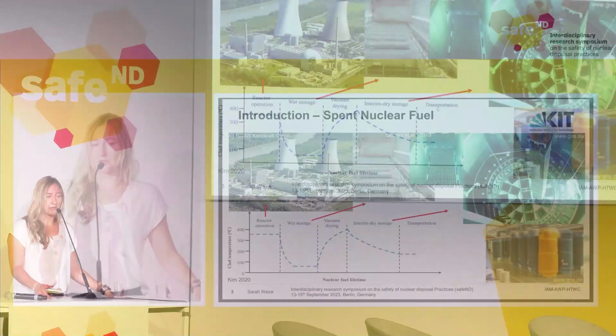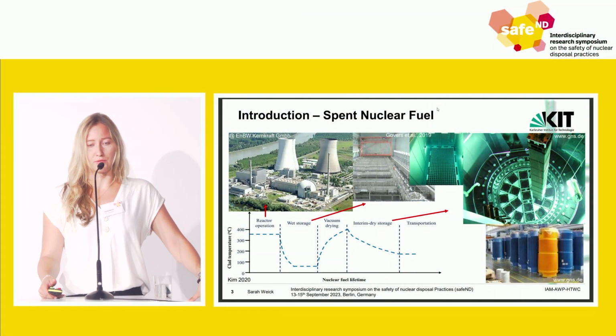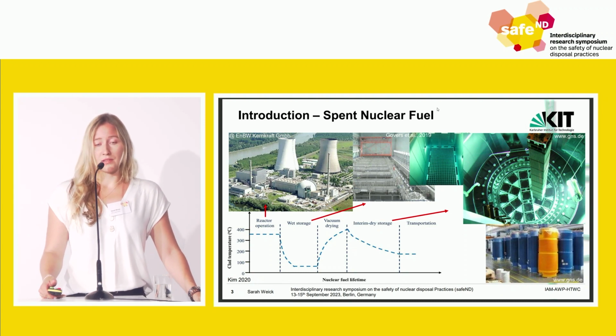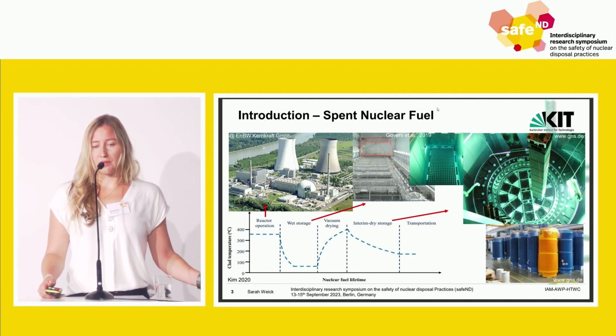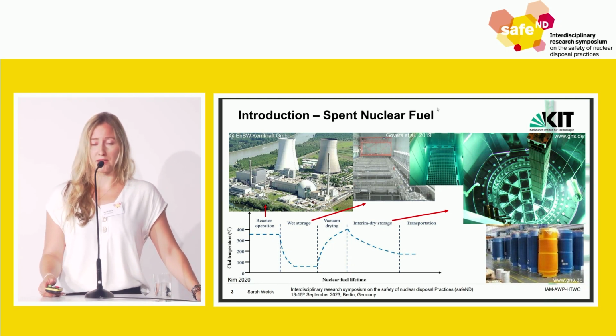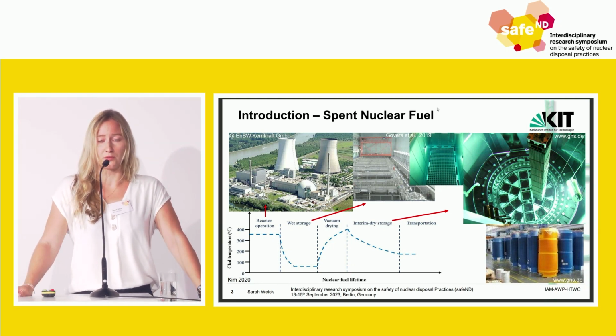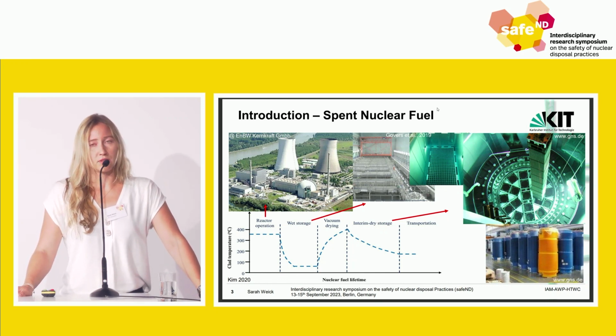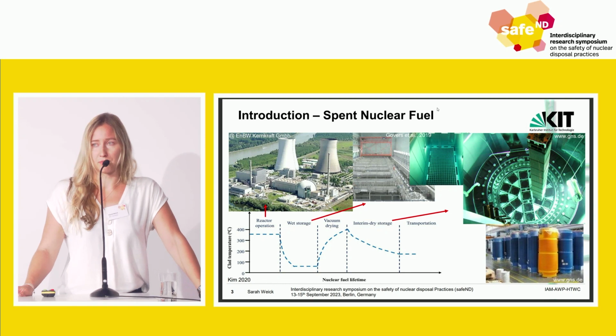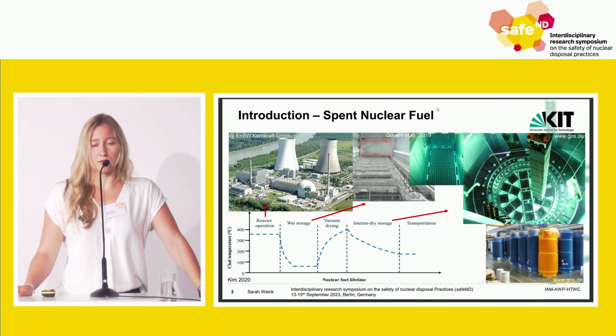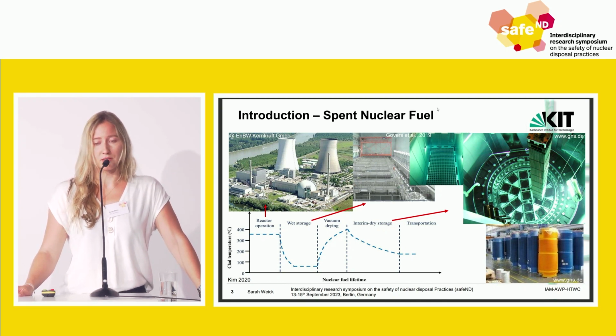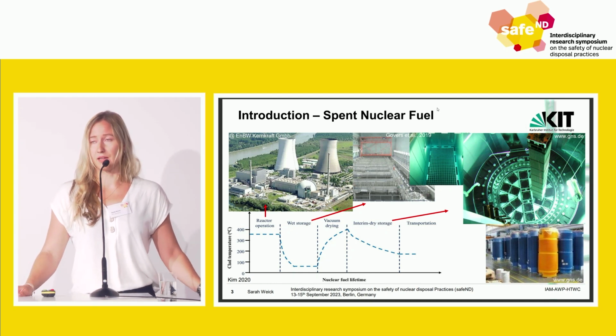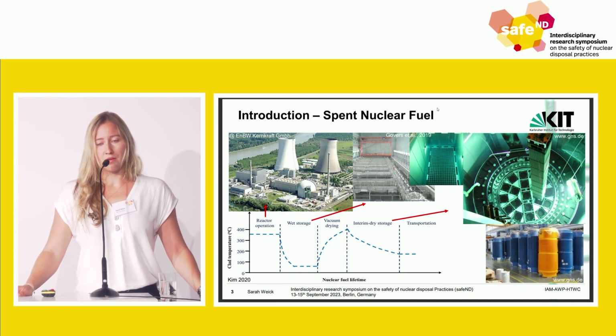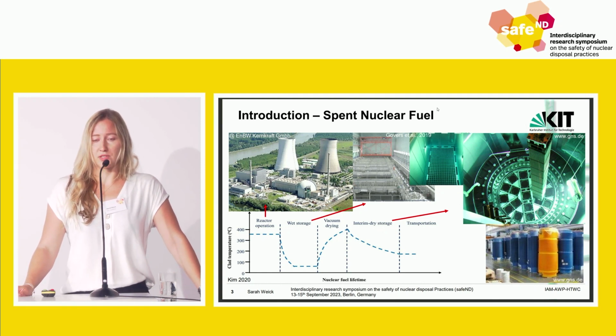To give a short introduction about spent nuclear fuel or its lifetime: we have the reactor operational phase, then a wet storage phase, a vacuum drying phase, and the vacuum drying phase ends with a temperature rise of about 400 degrees. These 400 degrees are basically the starting temperature of the interim dry storage phase relevant for the project. This period is characterized by a very slow cooling process lasting decades, and since we don't have a final repository yet, we eventually reach very low temperatures again.